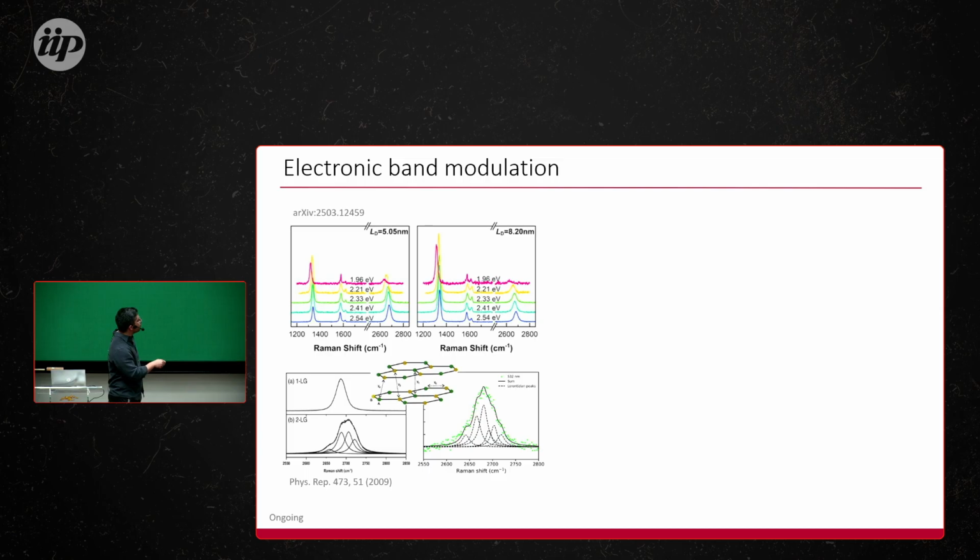However, for the doped samples, considering this wavelength over here, 2.3 eV, for bilayer, I don't have 4 peaks. I actually have 6 peaks. So we are not so sure why we have that. Basically, we have new scattering channels for the electron because of the defects that we are incorporating into the lattice. And this is still ongoing. It's being investigated by a student of mine. So we are still trying to figure out what is happening.